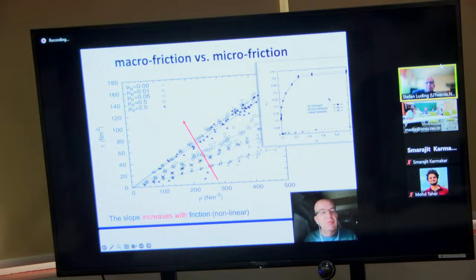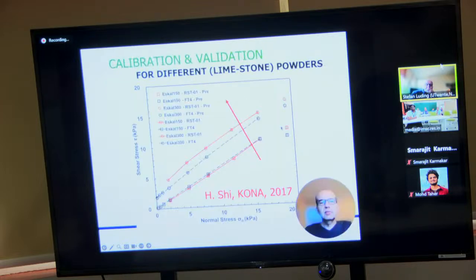However, when we plot shear stress against normal stress, here with units, we see that increasing particle contact friction coefficients give us an increasing slope of this friction law, this mu of I law. And this is the slopes plotted against the particle friction coefficient. So it's increasing and then it's saturating. This is what we can get easily out of it.